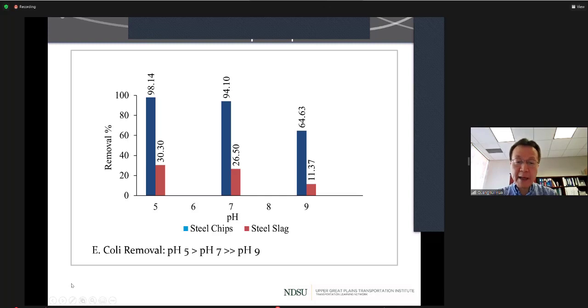And we also looked at the pH impact. We know that the stormwater runoff pH can vary based on the road conditions and seasonal variations. Based on our batch adsorption study, we learned that acidic pH can help the removal of E. coli. However, the difference between pH 5 and the neutral pH is minor. We achieved good removal for the two pH values. However, at high pH values, the removal efficiency substantially reduced. So basically, we learned that under acidic conditions, steel chips and steel slag had a better performance compared to alkaline pH conditions.